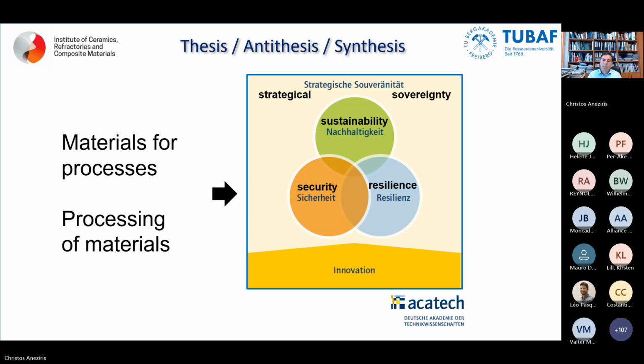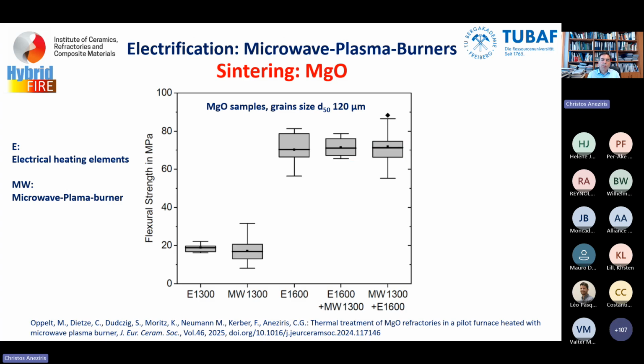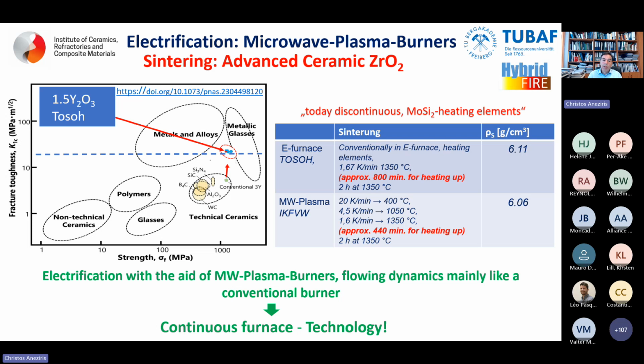Some results with the laboratory, small device: we have seen that in case of magnesia, fine magnesia, independent of whether you have electrical heating elements or mixed with microwaves, we have the same level of strengths. We have seen in case of zirconia, which is an advanced ceramic with high fracture toughness, but also a material which is very interesting due to its ionic conductivity or electrical conductivity above 1000 degrees Celsius.